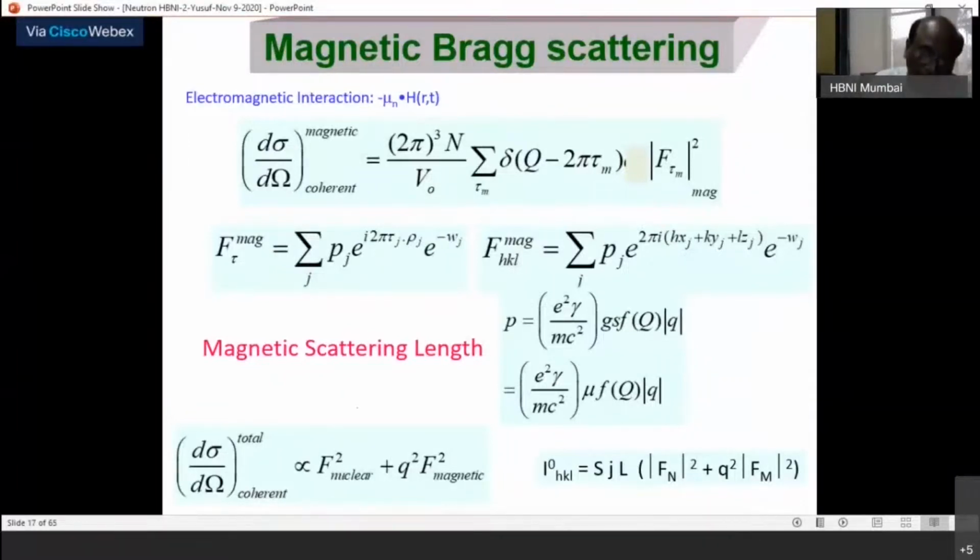For certain antiferromagnetic material, new Bragg peaks appear at a different 2 theta, while in the paramagnetic phase, when the moments are not magnetically ordered, those peaks are absent. So an additional, lower symmetry is involved. That is why this tau need not always be the same, and can be very different from the corresponding nuclear part.